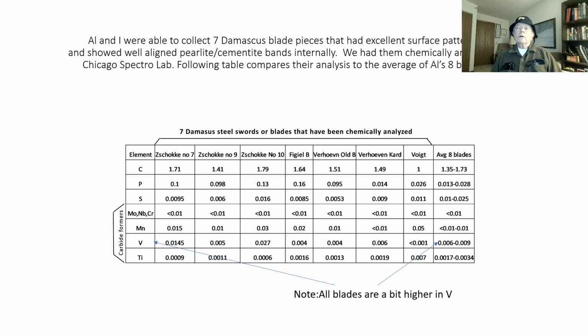So we took those blades, cut them in pieces after looking at them on the microscope. So we had the internal chemistry, and we also had the microstructure variation of those blades, and also 8 blades that I made. Here is a table showing the variation of the chemical analysis of the blades. Here's the average of Al's 8, and here's the average of the 7 good blades we had from collections.